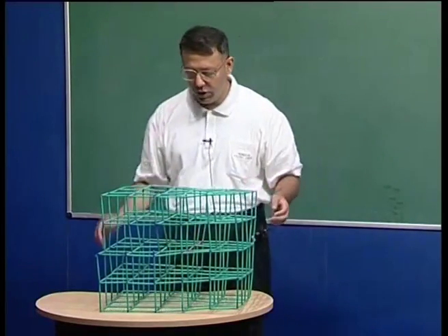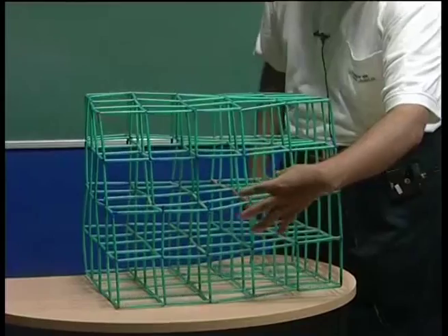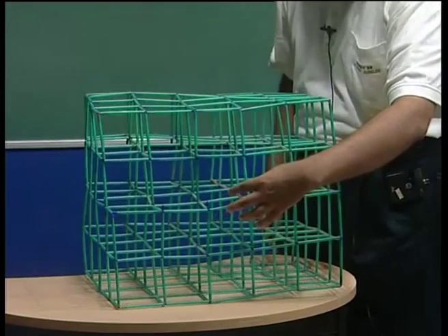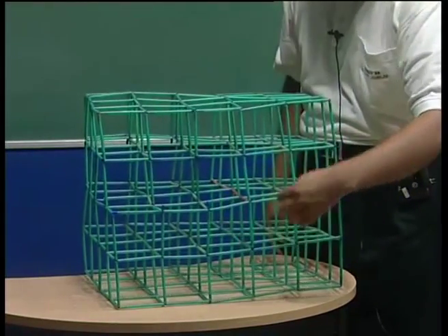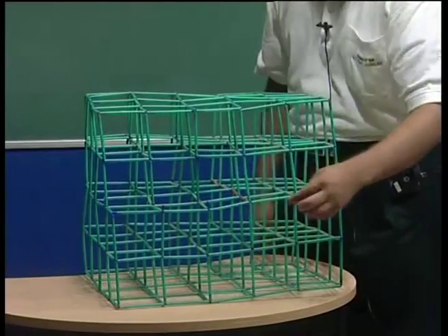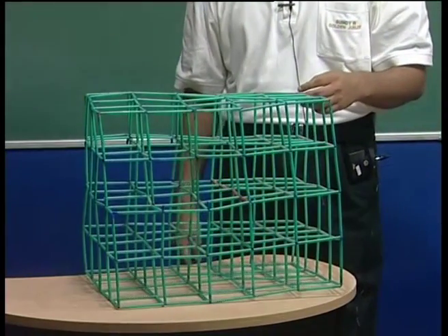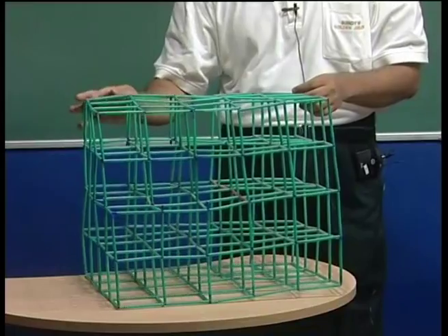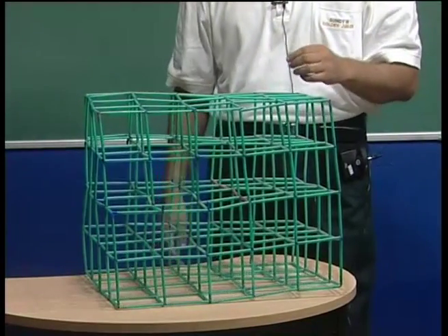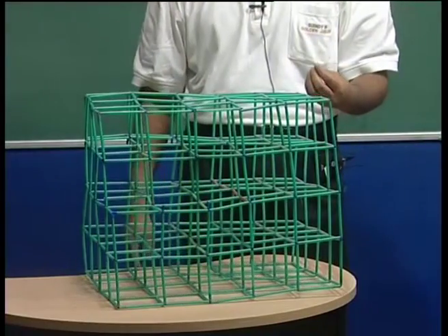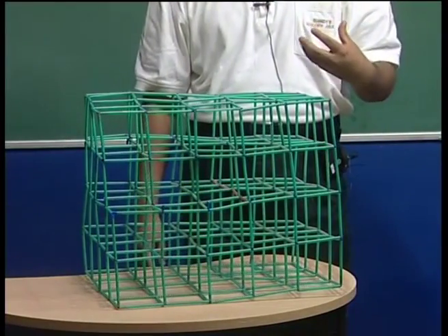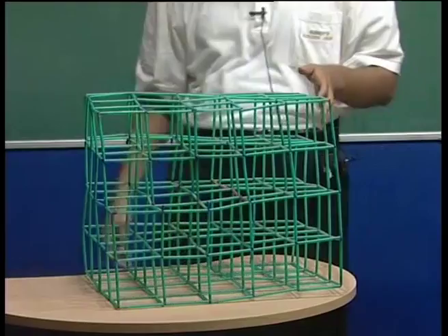Now, this region of distortion around this dislocation line again is so large that the elasticity theory would break down, and therefore this region I would call the core of the dislocation. But now, this core region is not associated with the kind of free volume we talked about in the case of edge dislocation, and typically we will see later that a screw dislocation would interact with other kind of defects which have again a shear field associated with them.